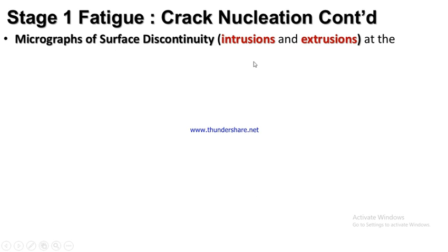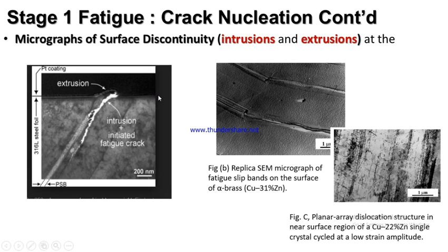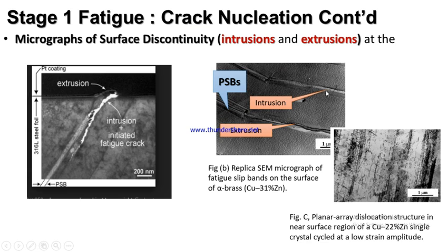We also use a micrograph to explain this. Let me put the micrographs here. You can see this is a micrograph showing an intrusion and extrusion taking place. This is an extrusion at the surface of the material, and this is an intrusion. These are dislocations occurring in the material. These dislocations lead to slip bands taking place, like I explained in the previous slide. This is another micrograph, an SEM showing slip bands. You can see this is a PSB, and this particular part is called an intrusion. The part that goes inside is an intrusion, and the part that protrudes out is called an extrusion.